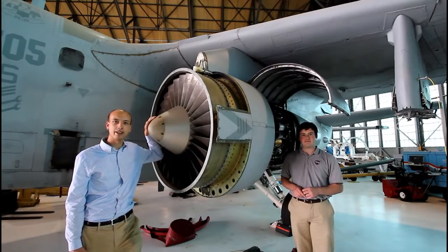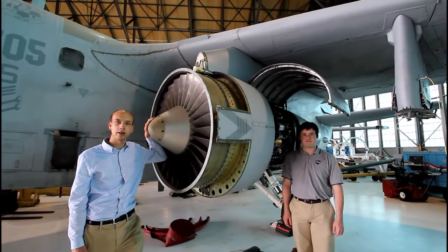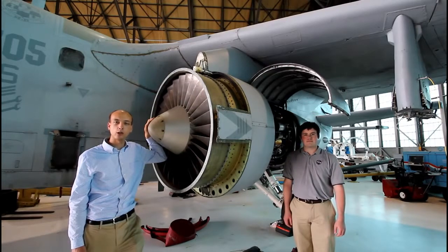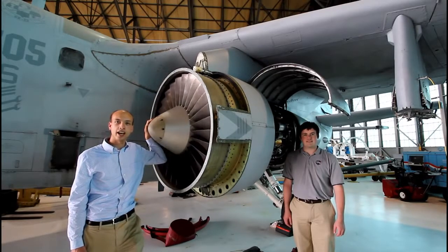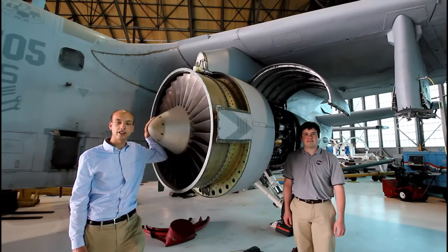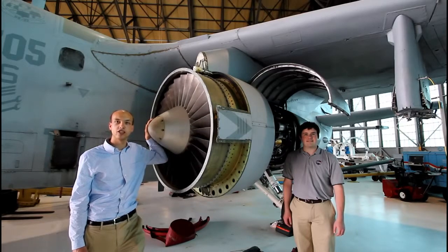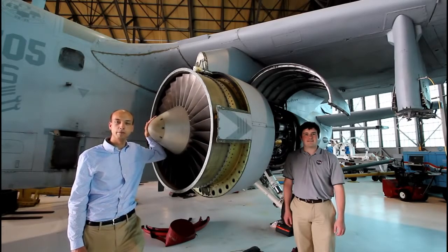The advanced powder metallurgy alloy, ME3, was developed in the NASA High-Speed Research Enabling Propulsion Materials Program in cooperation with GE Aviation and Pratt & Whitney Aircraft Engines. This alloy was designed to have extended durability at temperatures up to 700 degrees C in large disks.